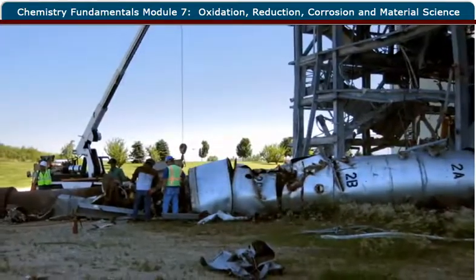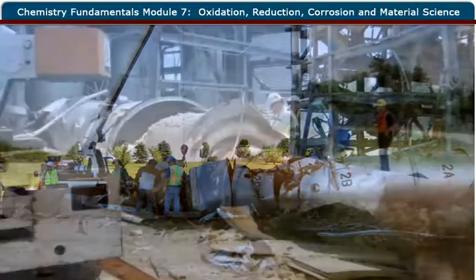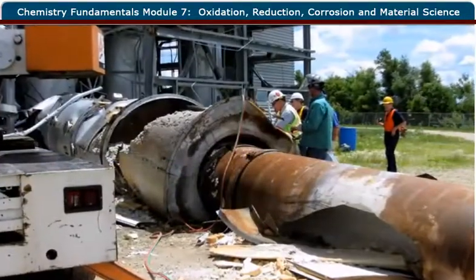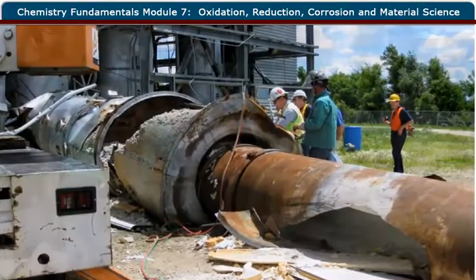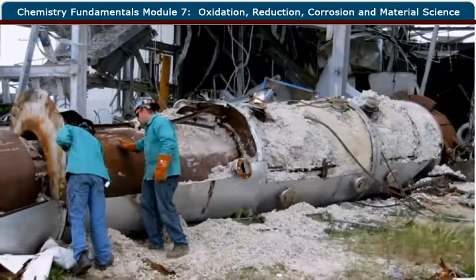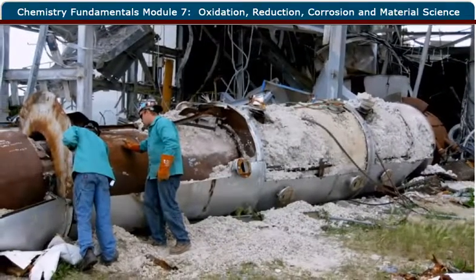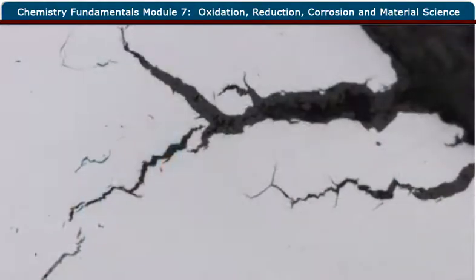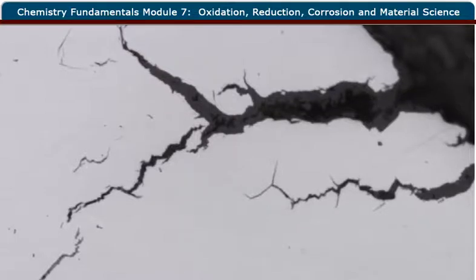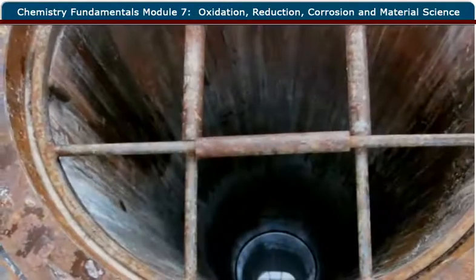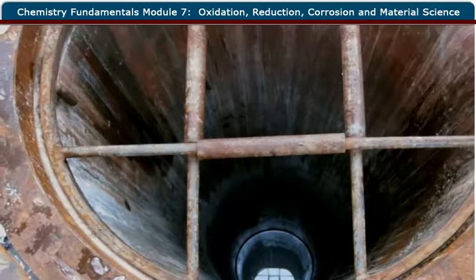To determine the cause of the failure, the CSB reviewed process data from vessel number 2 and worked with the National Institute of Standards and Technology, or NIST, to examine results from metallurgical testing. The investigation concluded that the failure most likely resulted from stress corrosion cracking on the inside walls of the vessel, which had gone uninspected and undetected for years.